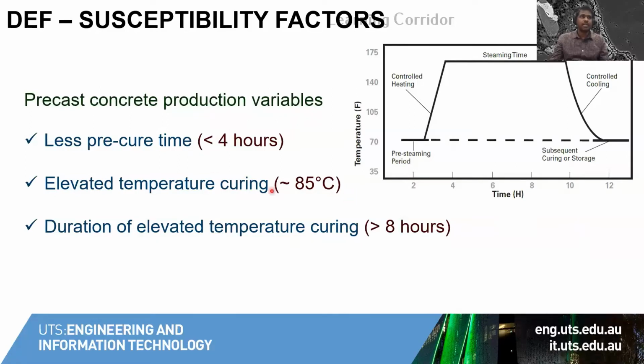So we already discussed the elevated temperature, and then the duration of elevated temperature curing, which is the steaming period. Here, the example is about 6 to 7 hours. More than that, exposing to a high temperature gives more chances of decomposition of ettringite in the system. And also, the higher temperature will keep the alkalis and the sulfates in the pore solution, not allowing the sulfates to contribute to hydration products formation, say monosulfates or other aluminoferrates and ettringite formation. So the more time the sulfates remain as free sulfates in the system, the more the chances of delayed ettringite formation